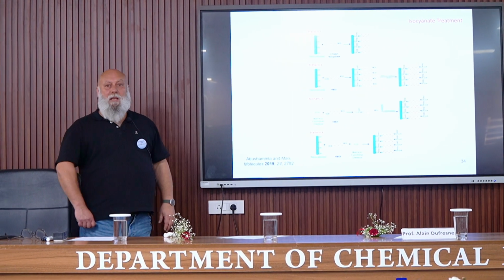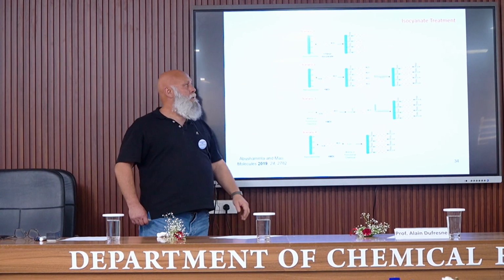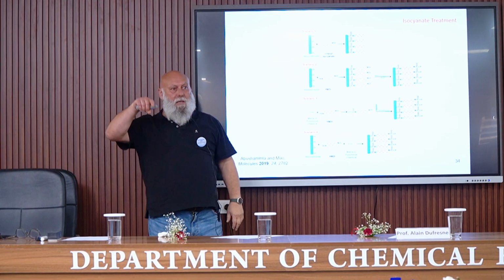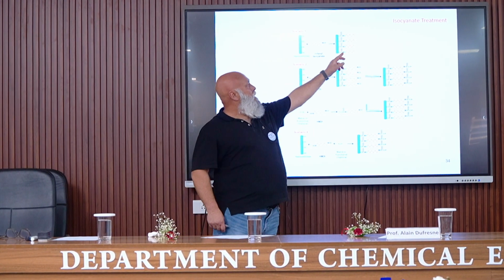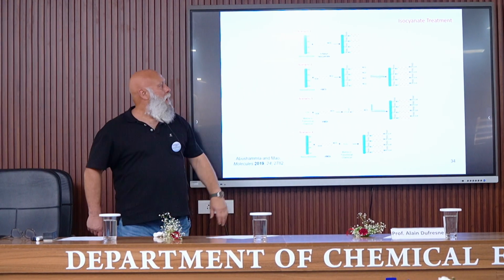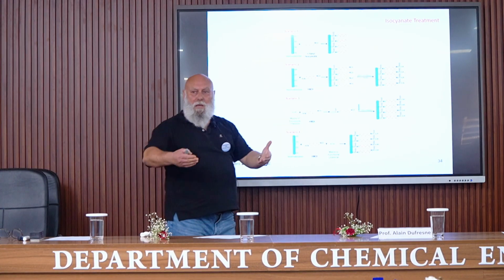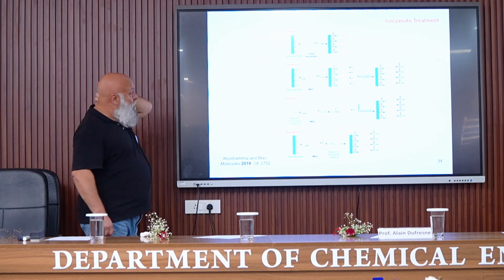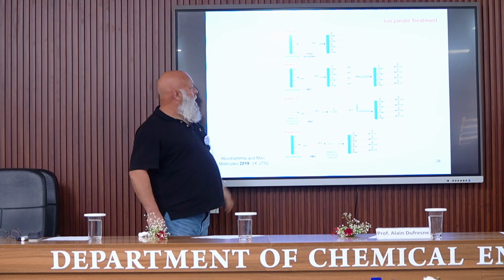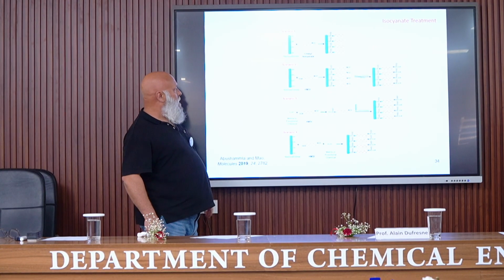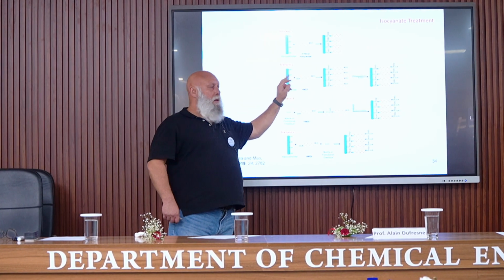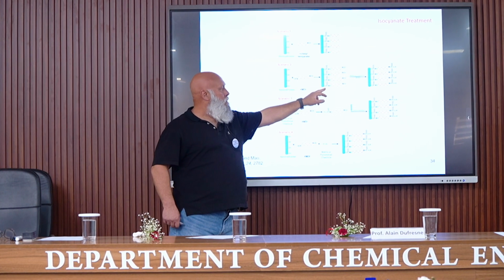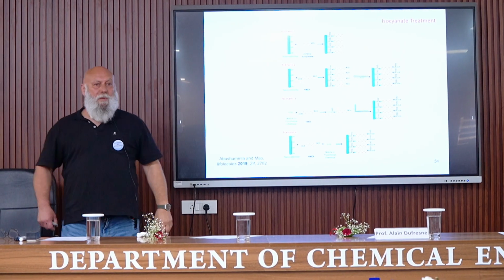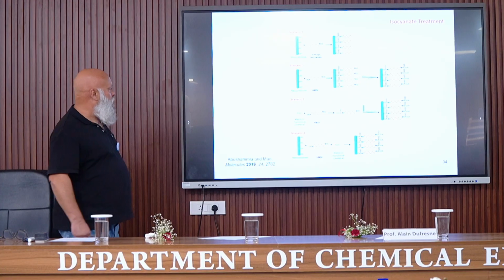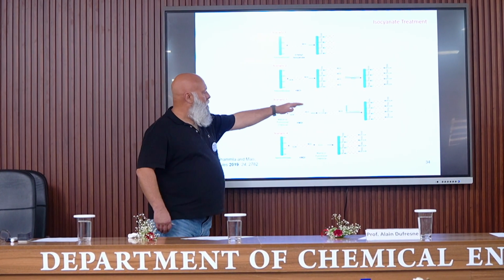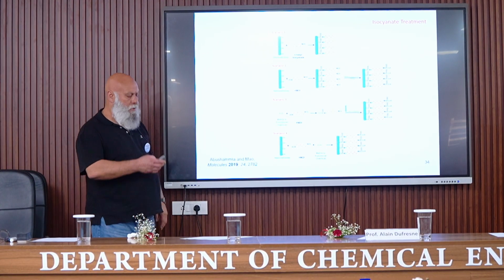And these are the different scenarios when using a monoisocyanate. So it means that we have only one NCO group on one end of the molecule that reacts with the OH group from the surface. And so, of course, we have here an aliphatic chain, meaning that the fiber is now more hydrophobic. We can use also diisocyanate, and here there are different scenarios. So we can have a reaction of one OCN group with the surface of the fiber, and the free isocyanate group is free to react with some functional groups from the matrix. Or we can have different reaction paths, but that result in the same final product.